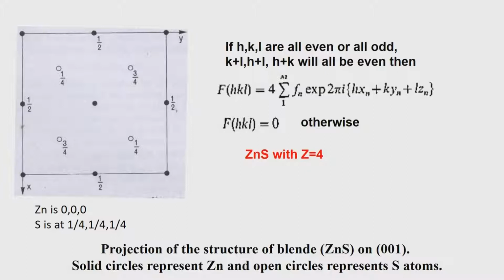So, we will take the zinc blende. It has been found by crystallography that there are 4 zinc sulfide units in the unit cell. So, the compound ZnS occurs 4 times inside the unit cell, and that is the information we have from determining the density of the crystal. Then we determine the volume of the unit cell by determining a, b, c, alpha, beta, gamma.